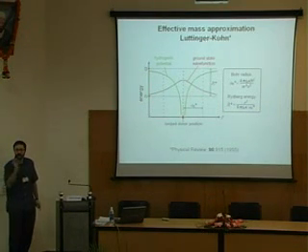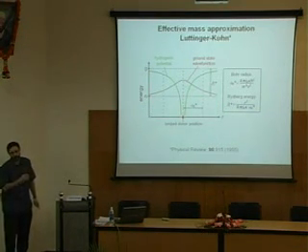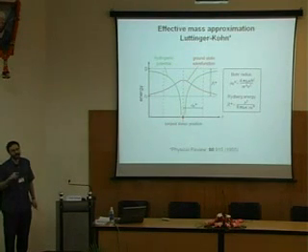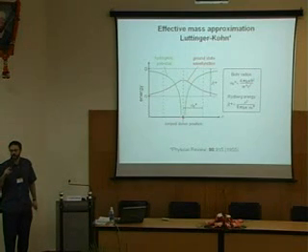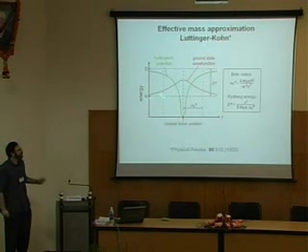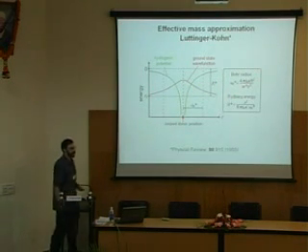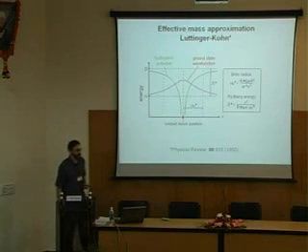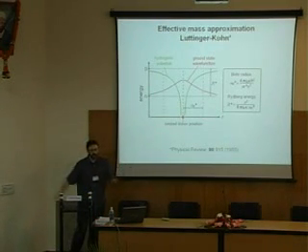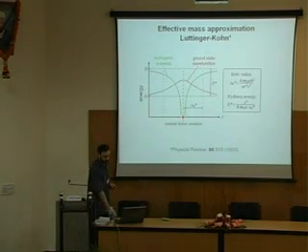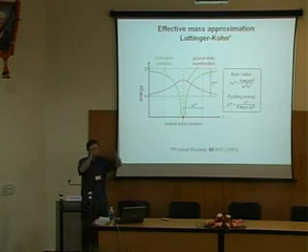So the electron onto these donors or acceptors, I have to say a hole bound to an acceptor, or an electron bound to a donor, is very weakly bound, only 5 millielectronvolts or so. And it's very much spread out. This parameter of the Bohr radius ends up being on the order of 5 or 10 nanometers, or at least 2 nanometers. So many lattice sites. And if you remember my schematic from earlier, I drew the electron really spread out on top of that plus sign.